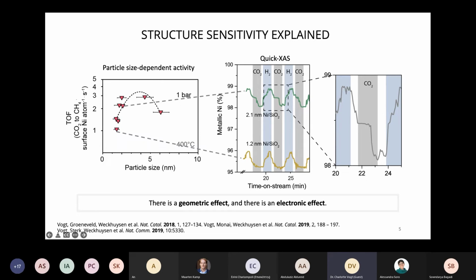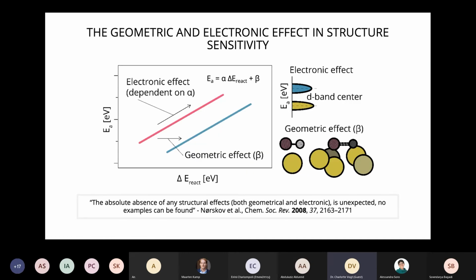So we were able to see with quick X-ray absorption spectroscopy, which you can see here on the left, that we were able to pulse back and forth between CO2 and hydrogen, and see that the ratio of metallic nickel changed during the reaction. So it ever so slightly oxidized and reduced the surface. And we were able to observe two different speeds of things happening during one pulse, which means that there have to be two different types of things that can go on at a surface within one pulse. So this is the geometric effect mainly, and smaller nanoparticle sizes always oxidize a lot more. And this is the electronic effect mainly. So structure sensitivity we understand. We understand why it's there. There are two main contributing factors: geometry and electronics.